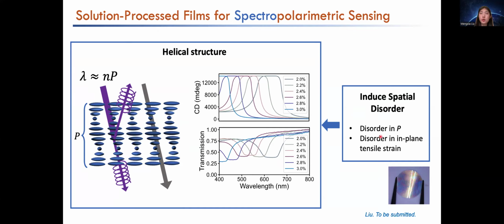We try to induce spatial disorder. If we increase the disorder in the periodicity, we are able to broaden the transmission wavelengths. And also, if we add disorder in the in-plane direction by creating some tensile strain in the material, we are able to generate some linear component in the optical response.